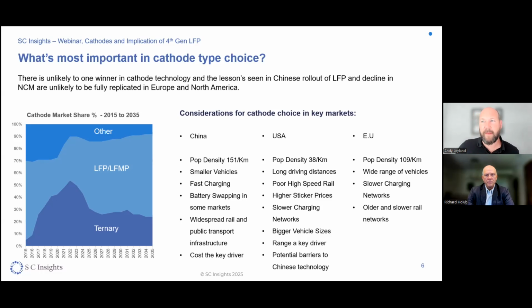And really, what was happening there is people were designing these batteries for a performance basis. And that's because they were very worried about range anxiety and charging anxiety. That was seen as the number one barrier to entry. Now, in China, that's slightly different. In China, we've seen this huge explosion in LFP, where LFP is taking up 70 or 80% of the domestic market at the moment.